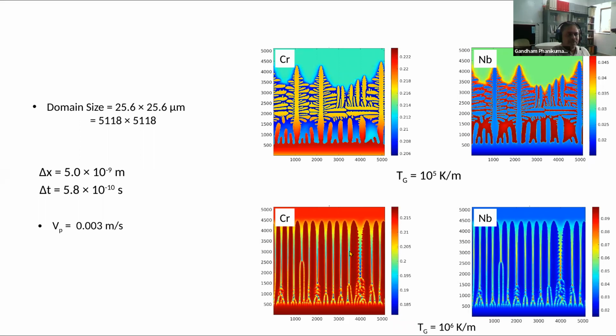And therefore the spectrum of compositions explored also is different. You see that the segregations are much more severe when you have got the interlocked regions in the lower gradient, but in higher gradient, you do not have that problem. There's hardly any region that is red in this domain, which means that the segregations are not such a big problem. So that is a very clear indication that by playing with the gradient, you can actually obtain the segregations under control. So that's a first hint that we can get.